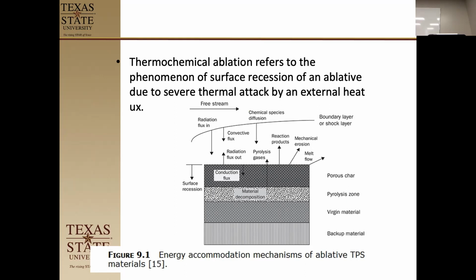And then the next thing we have is the stream of air as it's heading across here. There's a layer right across here that's going slower. It's like when you push water through a pipe, the water along the walls goes slower than the water in the middle of the pipe, right? So we're having that same thing happen here. But what's also happening is this is actually getting bigger and bigger as it ablates, because now we also have our solid particles running across it, and wearing it off. And because there's such high shear and flow here, any molten products in your char are going to melt and flow in the direction of the gas flow. Okay. So for each of these thermal protective systems, that's what TPS is for, we're going to end up with something with a huge char layer.